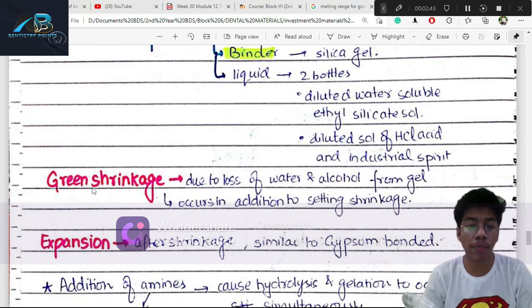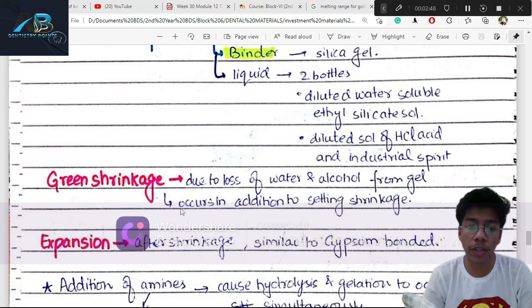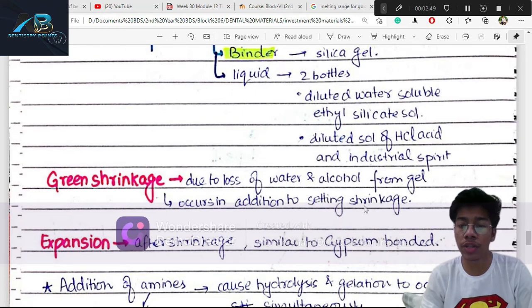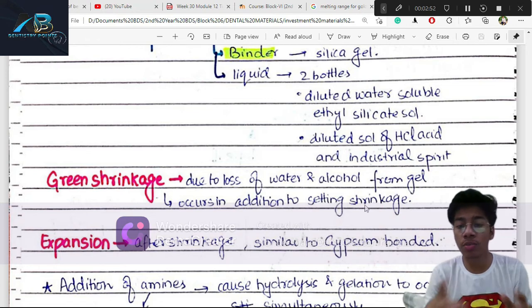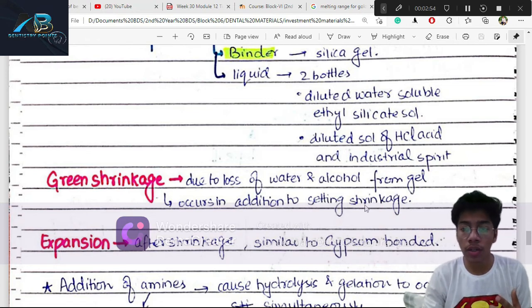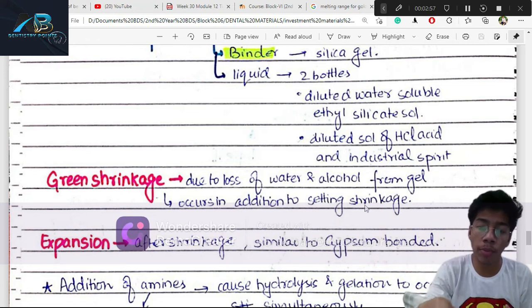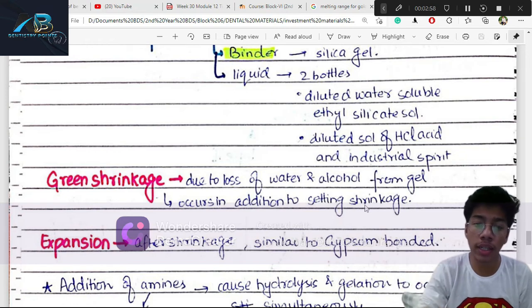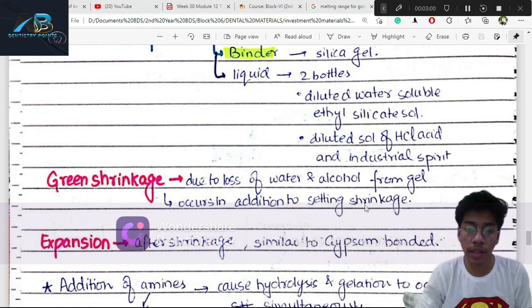The composition of ethyl silicate investment: the powder contains quartz and cristobalite as refractory material, with silica gel as the dry binder. The liquid consists of two bottles — a dilute water-soluble ethyl silicate solution and a dilute HCl solution in industrial spirit. Alcohol is created during setting, and these are flammable — a key adverse effect. There is also gel drying shrinkage due to loss of water and alcohol from the gel.